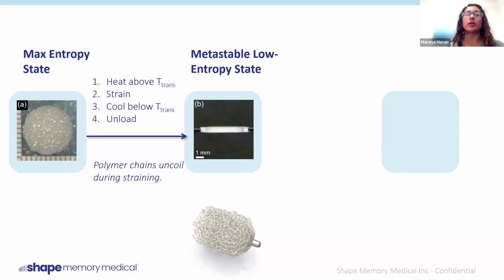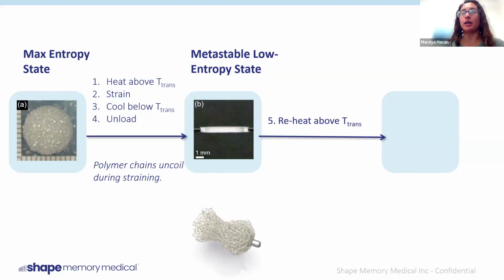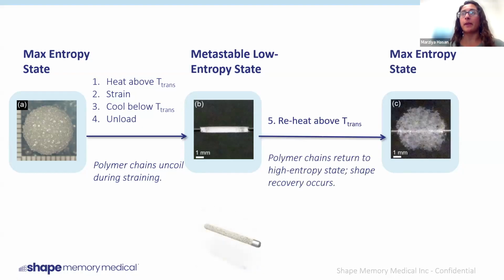And once we unload the strain, what we see is that the foam is in this metastable state where it is in a crimped rod geometry, but it doesn't necessarily want to be here from an entropic perspective. This is not the ideal entropic state for this material to be in, so it's just waiting for that external trigger to go back and return to its original geometry. So when we reheat this material above its transition temperature, it'll re-expand back to its original shape, into its preferred entropic state.